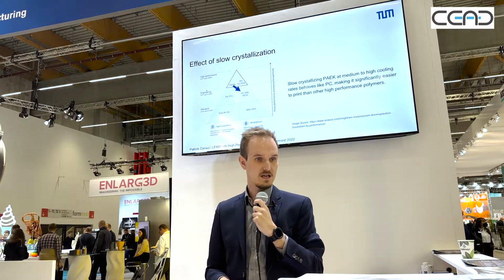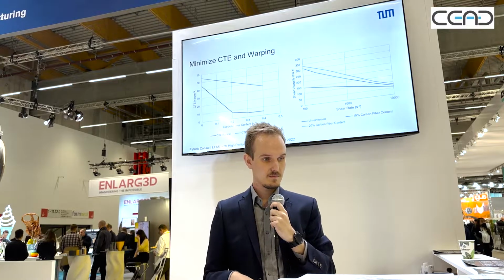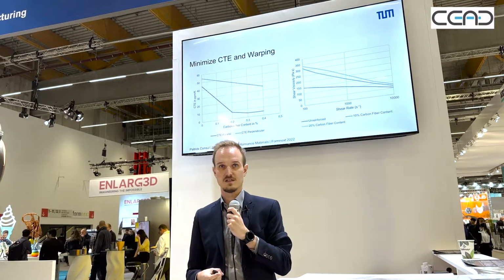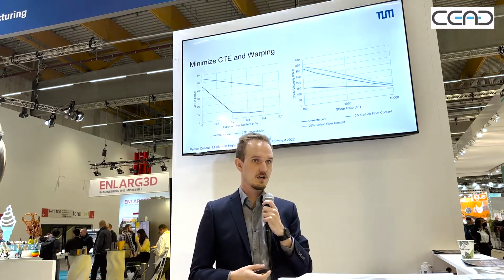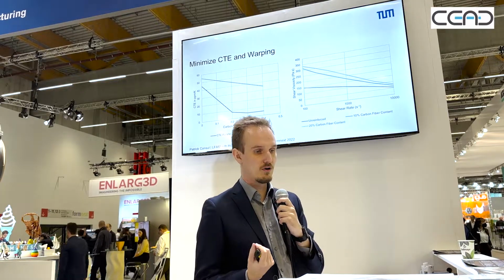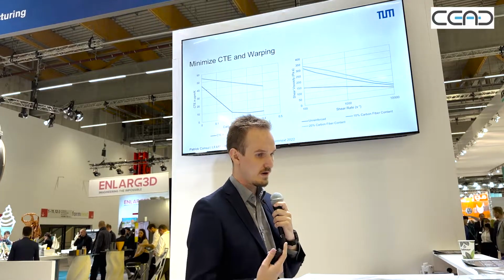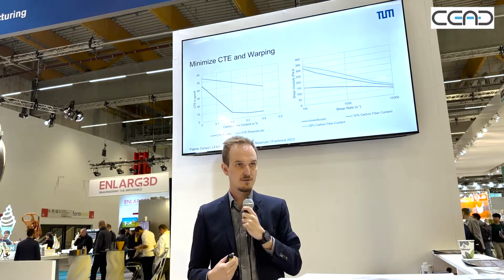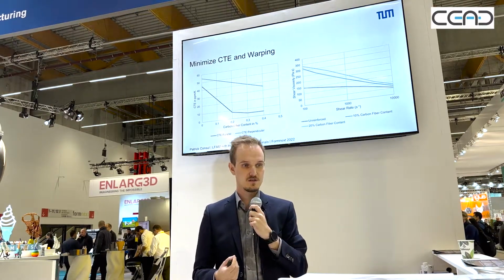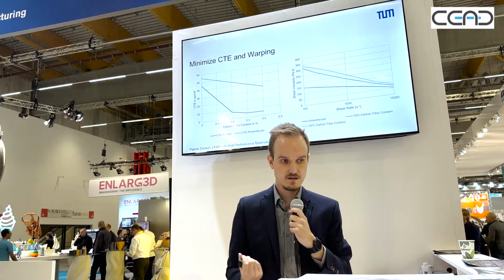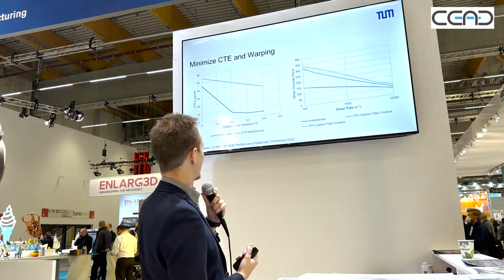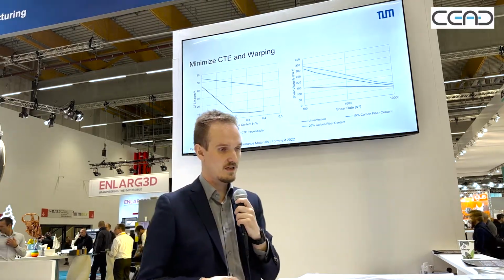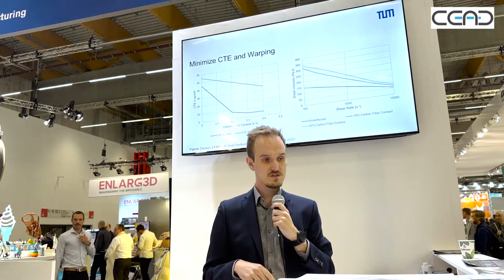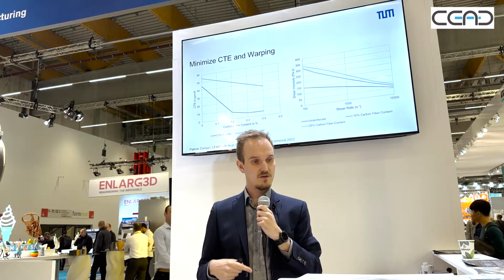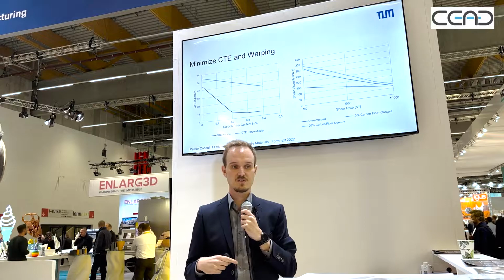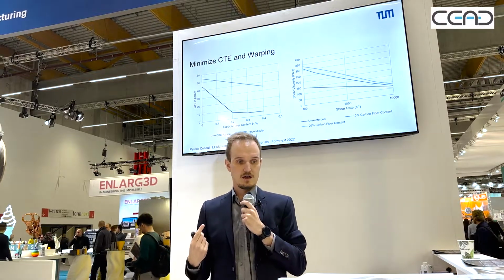So we had to look at minimizing the CTE, and an easy way to minimize the CTE is by just adding carbon fiber. The carbon fiber basically blocks the polymer from shrinking. So by adding more and more carbon fiber in your polymer, you can reduce the CTE quite drastically. And the picture on the left actually shows you how the CTE drops by adding more carbon fiber, and the one on the right is again the viscosity by adding more carbon fiber.